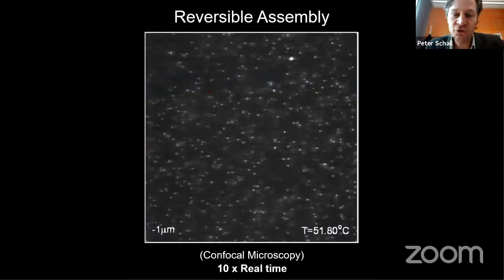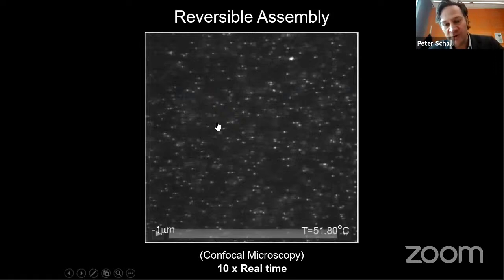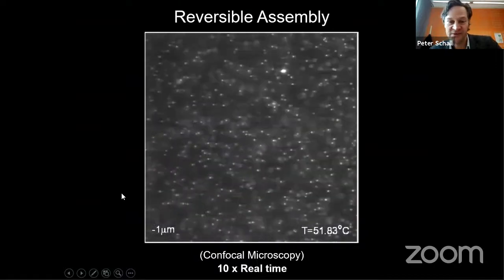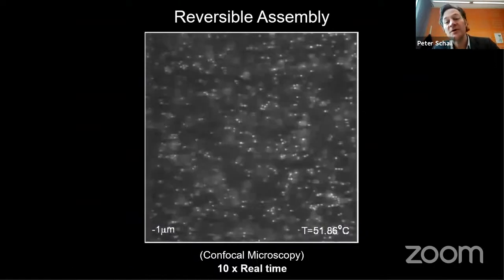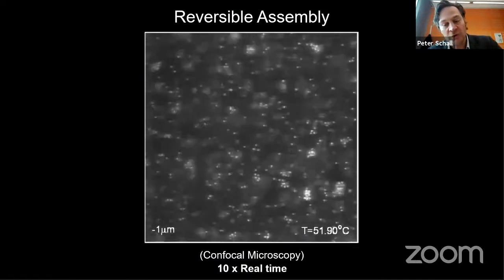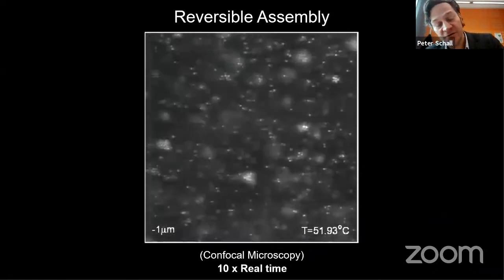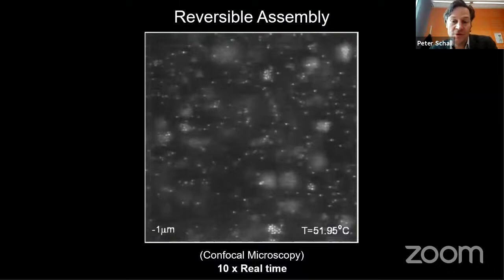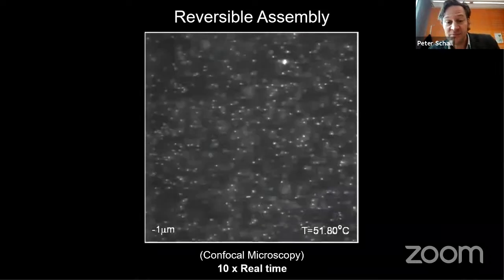Let me now finally come to show you some movies. If we just use spherical particles, such as here, right, and we keep, let's say, approaching the critical point, what we see is that the suspension, these particles, they're first suspended. Now we are going to approach the critical point more and more. They're actually forming clusters, and they're forming small, what you may call liquid nuclei, small liquid drops, and these drops will grow. So what you immediately see in a model system is here a colloidal gas to liquid transition. So you see that particles condense due to an increasing attraction, and they condense into these nuclei that then grow into larger and larger drops. So this system we could already study in terms of a gas-liquid separation.